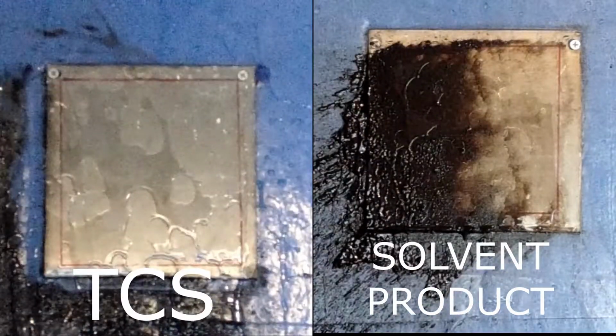Within 1 minute and 20 seconds, the TCS product completely cleaned the steel section, whereas the solvent-based product had cleaned just over 49%, which was mainly the thicker surface covering and allowed the harder to remove fine surface covering to remain.